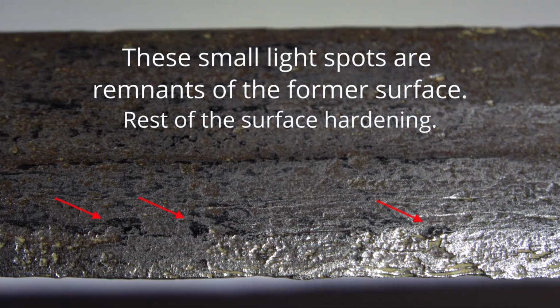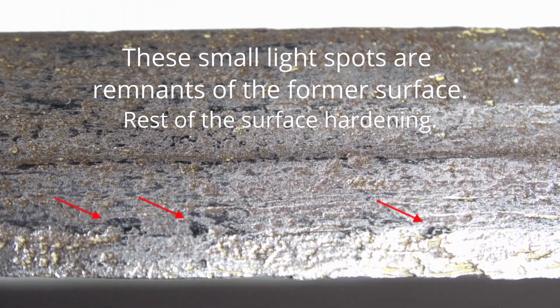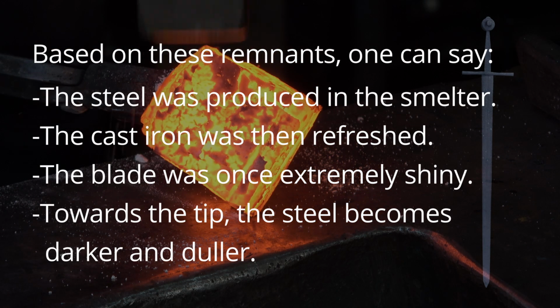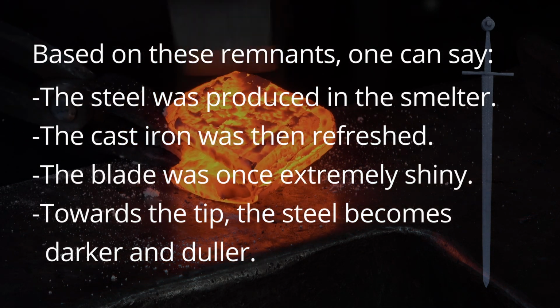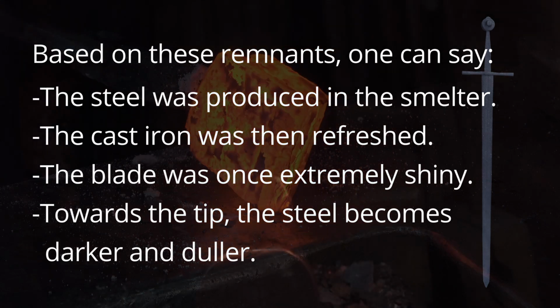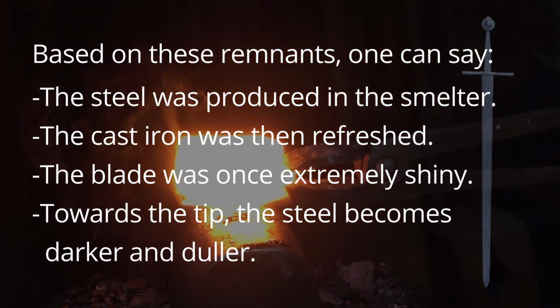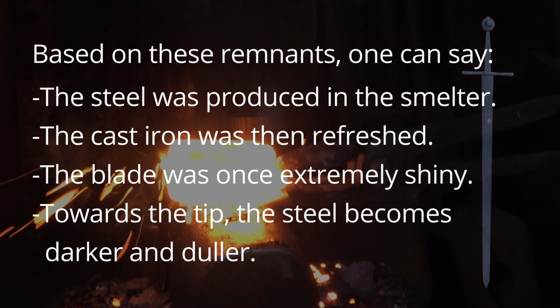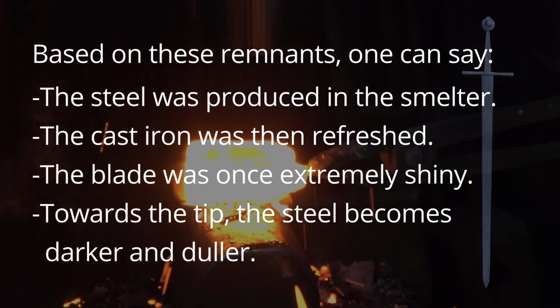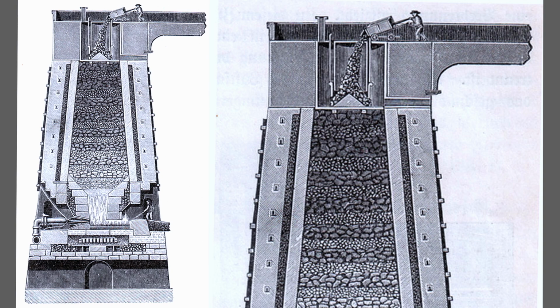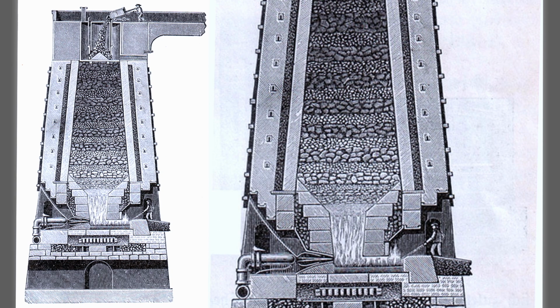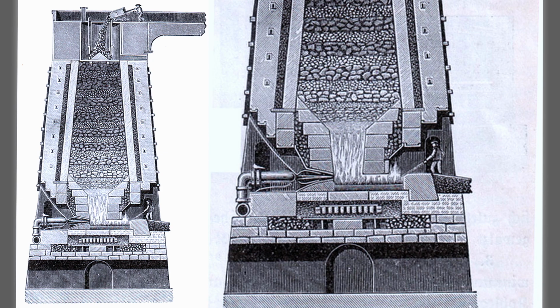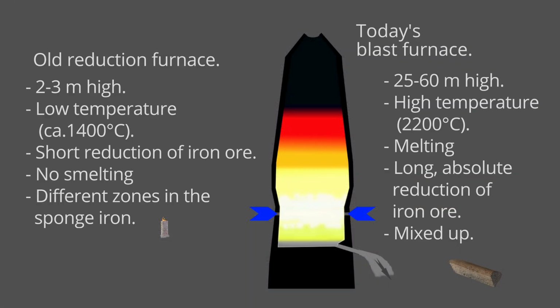The fire welding of steels is as old as steel production itself. Even the earliest steels had to be forged and fire welded in order to obtain a usable steel. The development of steel production in Europe was initially very slow. For 2,000 years, one and the same steel was produced, which never reached the smelter. In the 13th century, the installations were increasingly powered by water. The furnaces became larger, and some of them even managed to melt the steel. This was not at all desirable at the time.